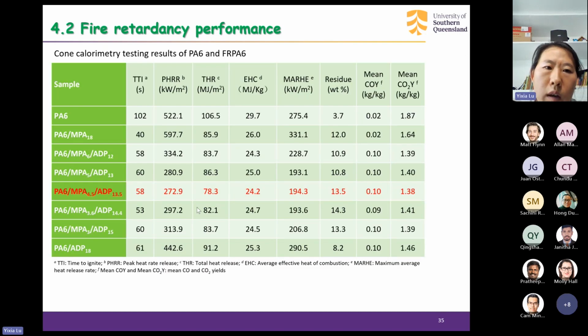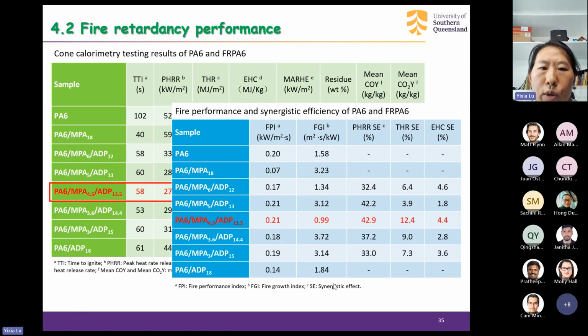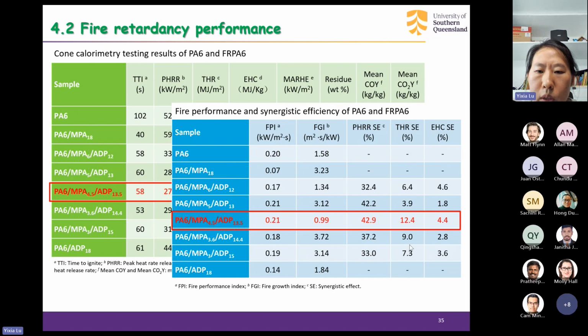As the cone test says, the heat release rate is also decreased. For this formula, with 4.5% of MPA and 13.5% of ADP, where the total addition amount is 18%, this formula presents the lowest PHRR values, with more than 40% decline. And we also investigated the fire performance and the synergistic effect. Luckily, we found that MPA and ADP show an efficient synergistic effect, and this formula shows best.